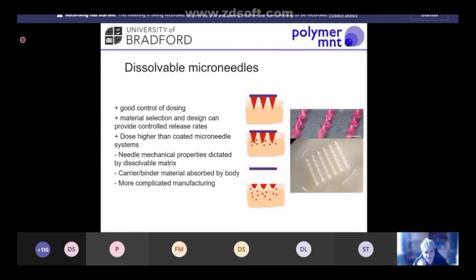The aqueous environment and the temperature can be used as triggers to cause this dissolution of the polymer that contains the drug. So basically what happens over time is the polymer will be absorbed or dissolves into the body and it's carried away, and the drug is then released into that affected area. So over time, those materials will either dissolve to nothing and then the backing can be removed. You can actually engineer sort of weaknesses at the union between the dissolvable microneedles and the backing plate. So you can actually remove the backing plate and leave the dissolvable needles in the skin. So they can dissolve over any period of time from just a few hours up to numbers of months if required for a whole range of delivery applications.